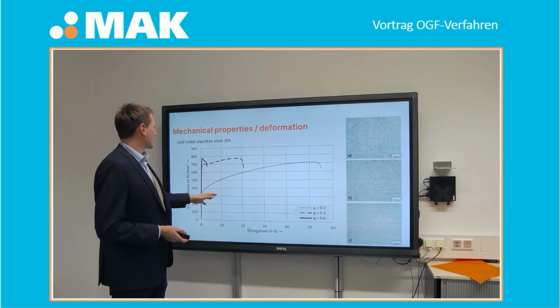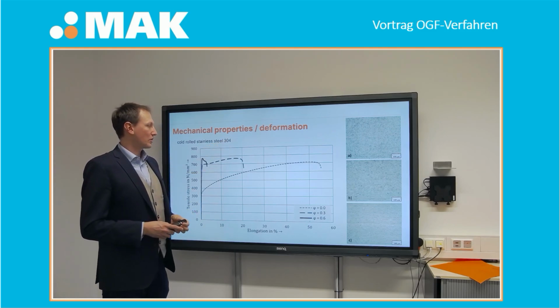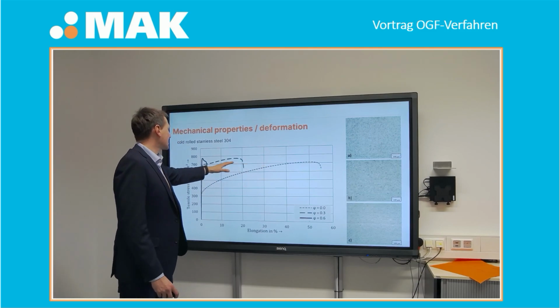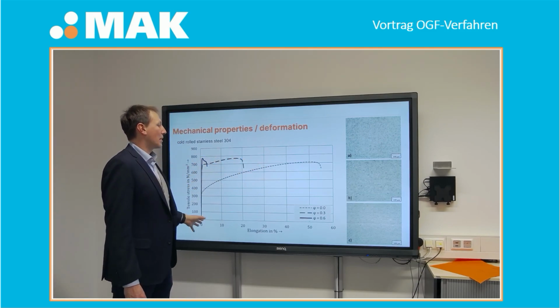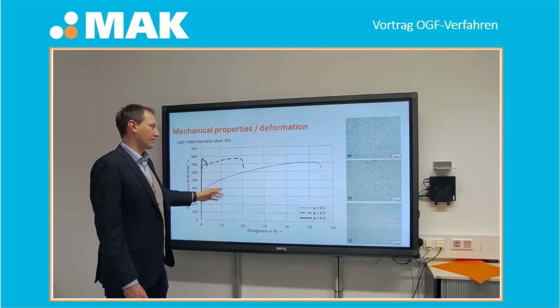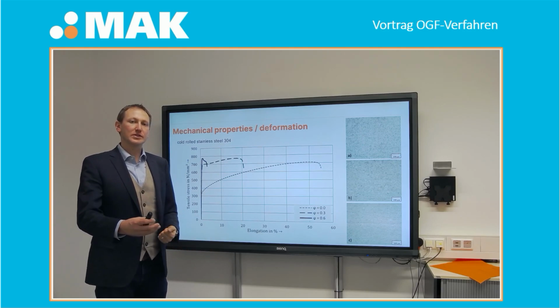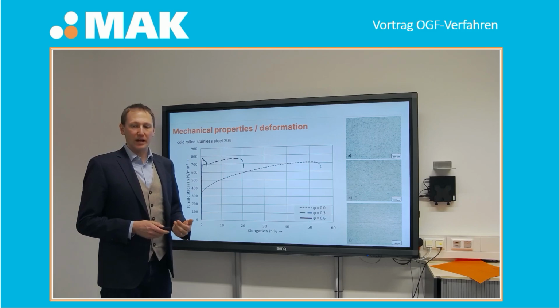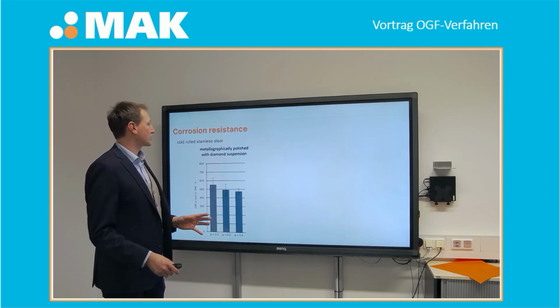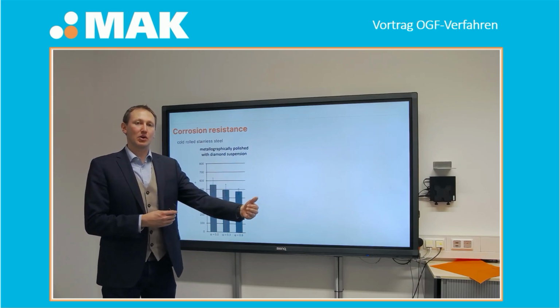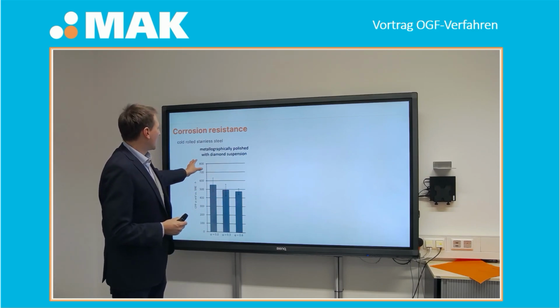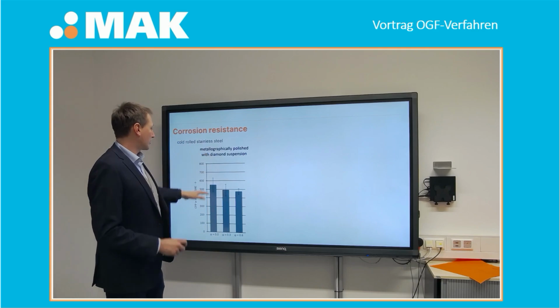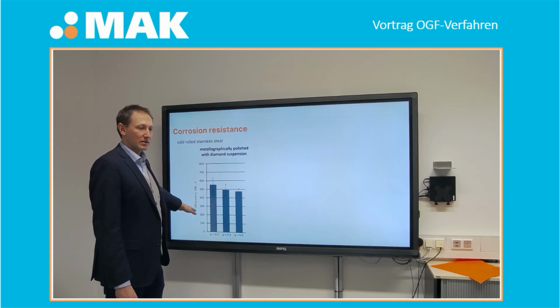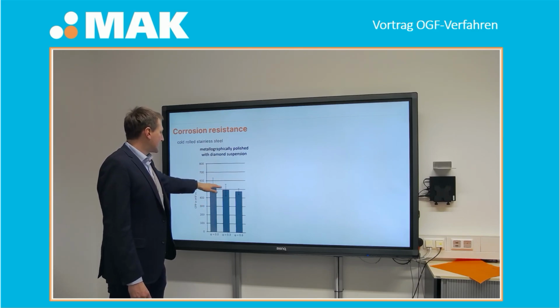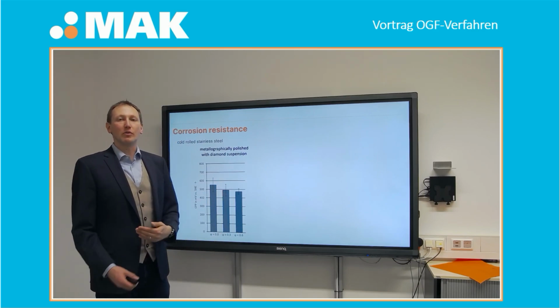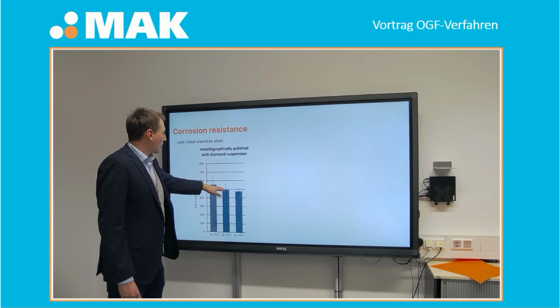But before we tell you something about the corrosion resistance, I will illustrate the change of mechanical properties by processes like cold rolling. Like you can see here, we have a stainless steel 304, and by cold rolling you have an increase of the tensile strength of the material and a decrease of the elongation at fracture. This was carried out in combination with different kinds of surface preparations. First, we did some cold rolling, afterwards some surface preparations, and with standard metallographic polishing in the laboratory, you can see the corrosion resistance, shown by the critical pitting potential, is decreasing with an increase of cold rolling of the material. It leads to a lower corrosion resistance.